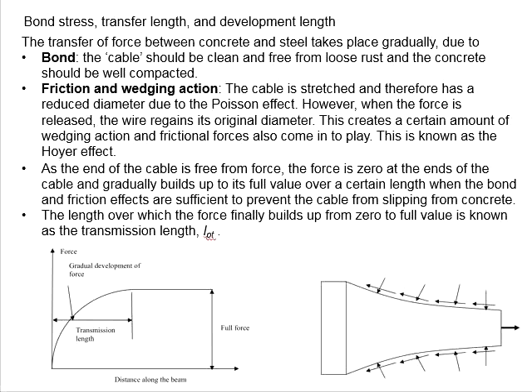The principle of pre-stressing concrete is by transferring stress from steel to concrete to generate compressive force acting on the member to counteract external load. In fact, the transfer of force between steel and concrete takes place gradually, mainly due to the bond between concrete and steel.